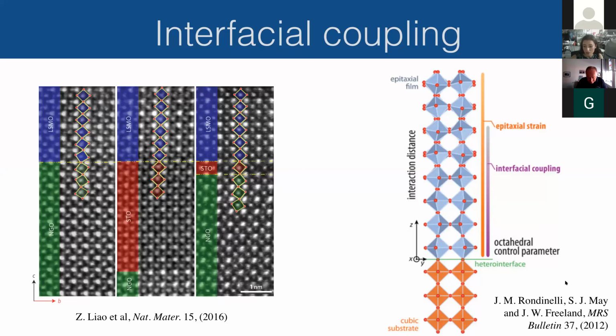If you are interested, I would say that this is ahead of its time actually, because they wrote this article before people were really looking at these kind of effects. So what they were saying here is that you have to not only think about epitaxial strain, which we know and we understand, and it goes over very many unit cells in general, but you also have to take into account interfacial coupling, which they show here as being something that is much shorter in range. And of course, given the strong lattice electronic coupling of perovskite oxides, this sort of effect, even if it's just a few unit cells, can be detectable, and it can be super important.